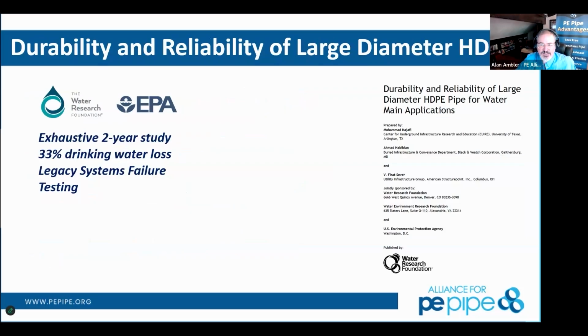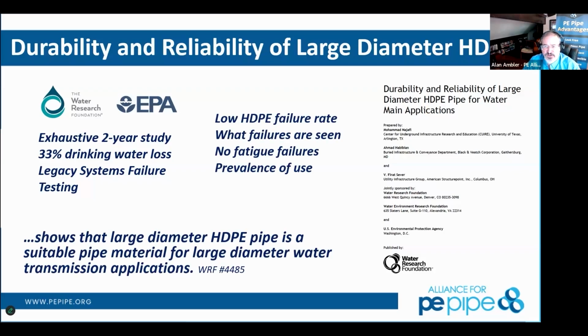I know that was quick, but this happens to be a little bit more focused on some of the rehab methods from here on out. That was great that we're getting good information on growth, continued growth within the industry. So, EPA and the Water Research Foundation have done some reports and information for us about the durability and reliability of HDPE in these larger applications, and this is one that's available for you as well, that you can review and study, not just what the PE Alliance has to say about it, but what the Water Research Foundation also has to say. So those low HDPE failure rates are going to help walk us down from that catastrophic failure that could really impact a larger diameter in that manner. And then we're now starting to grow it even more in that transmission system scenario.